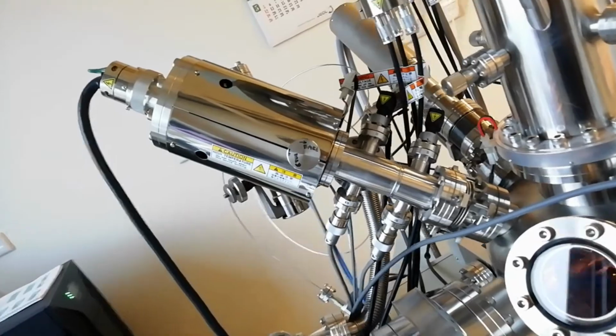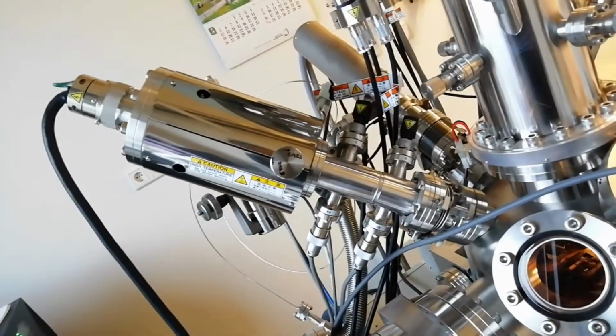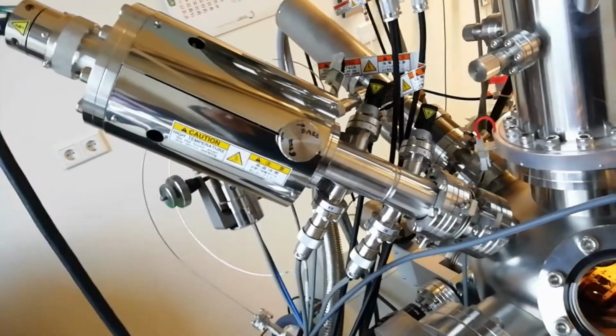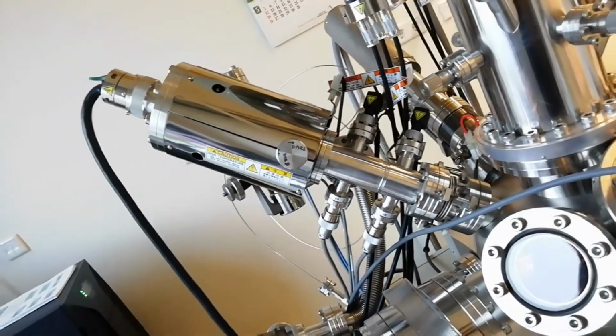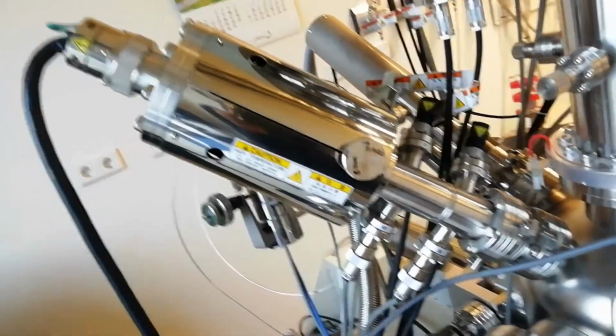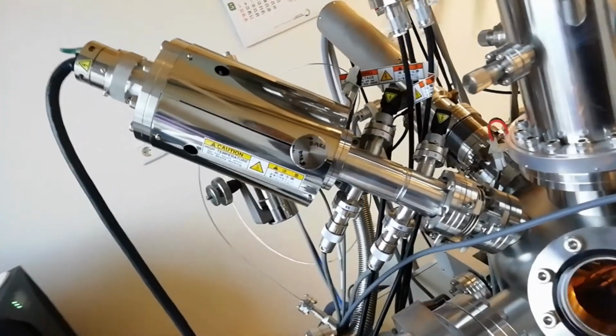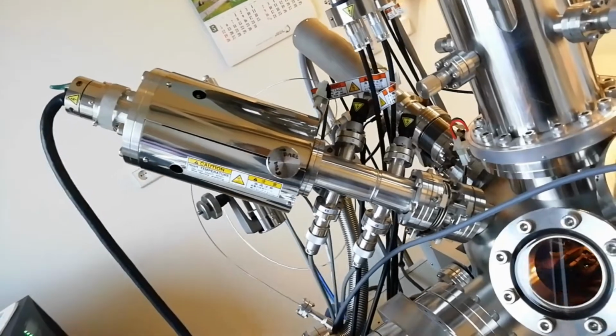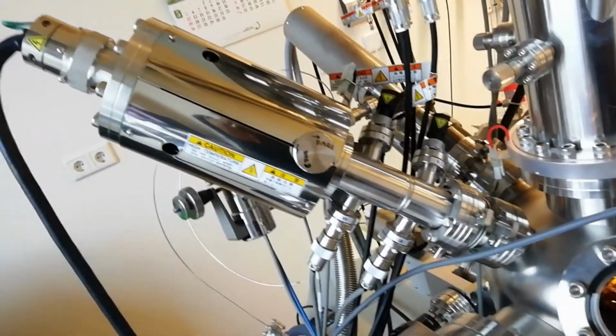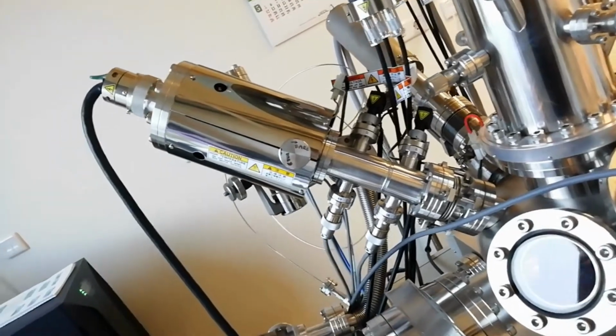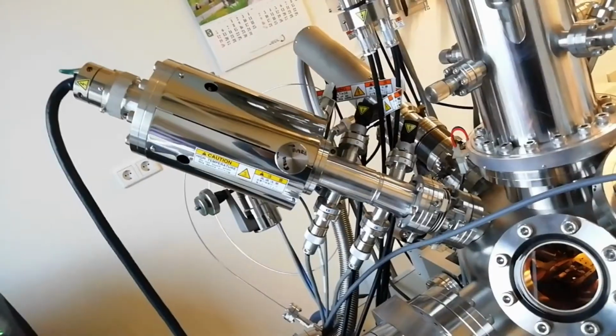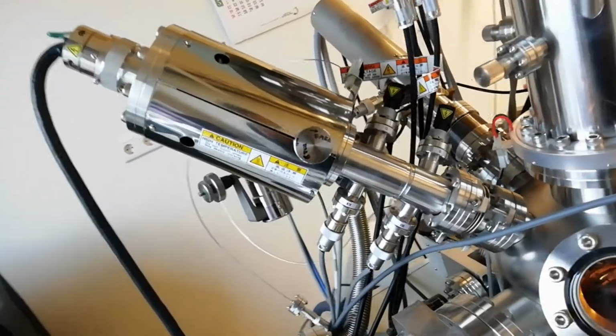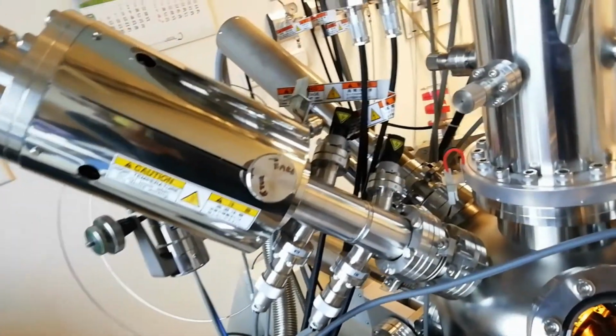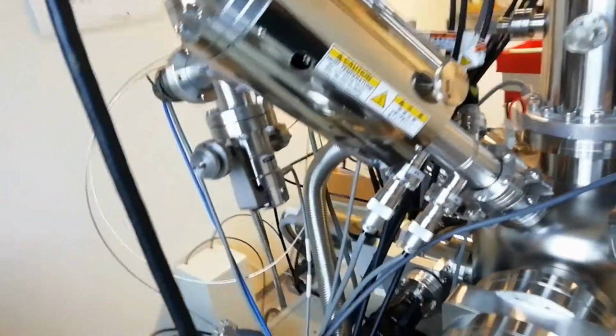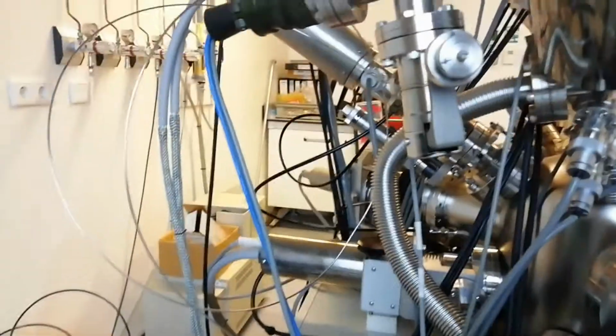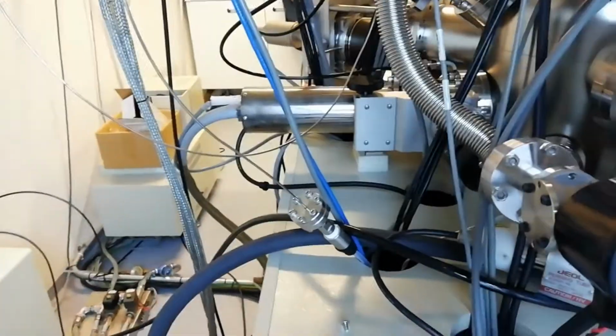Most XPS instruments include an ion gun that produces monatomic argon ions, Ar+, for this purpose. A range of beam energies is usually available, typically from a few hundred electron volts up to a few kiloelectron volts, allowing operators to choose etch rates depending on the thickness of the layers to be analyzed. Spectra are collected after each cycle of material removal by ion milling to generate a depth profile, typically displayed as atomic concentration, which shows the variation in the chemistry with depth into the surface. Depths up to a few microns can be investigated using this approach.